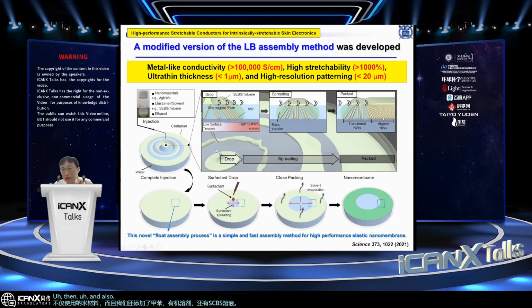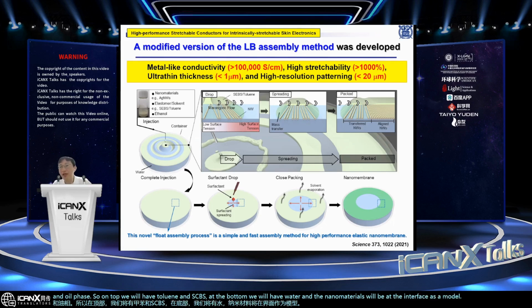And also we controlled the molecular weight of ligands, PVP ligands, around the nanomaterial, in this case, nanowire. Then the nanowires can be assembled as a monolayer between water phase and oil phase. So on top, we will have toluene and SDBS. At the bottom, we will have water, and the nanomaterials will be at the interface as a monolayer. And if we wait a few minutes, then toluene naturally will evaporate. Then on the top surface, we will have a very thin SDBS layer. At the bottom, we will have water.